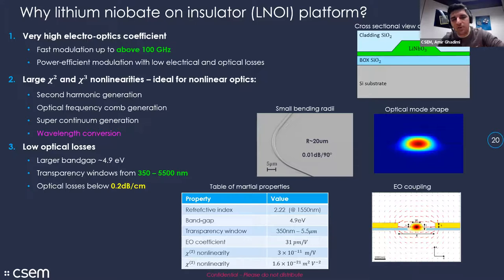For lithium niobate, this is around 4.9 electron volts. This allows us to put a lot of optical power in our circuits without having to deal with two photon absorption. And we can do it in a very wide wavelength window. Lithium niobate is transparent from 350 nm all the way to 5.5 microns. So it covers the wide range of visible, near or mid infrared, or telecom band. So you have a lot of wavelengths.